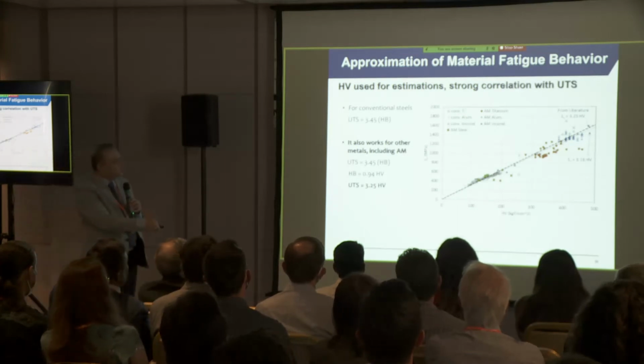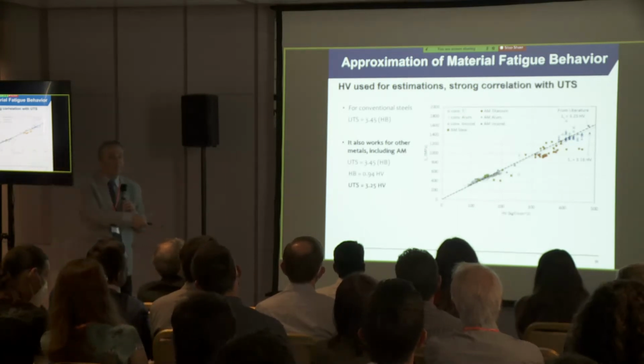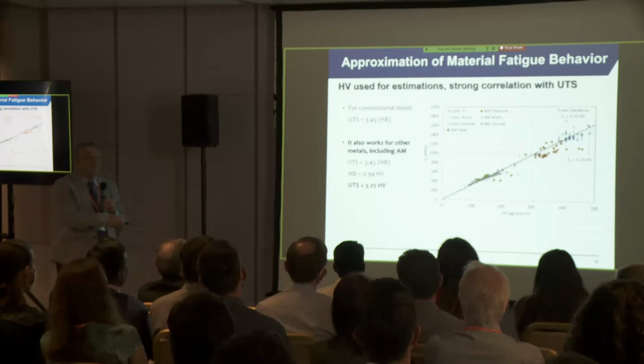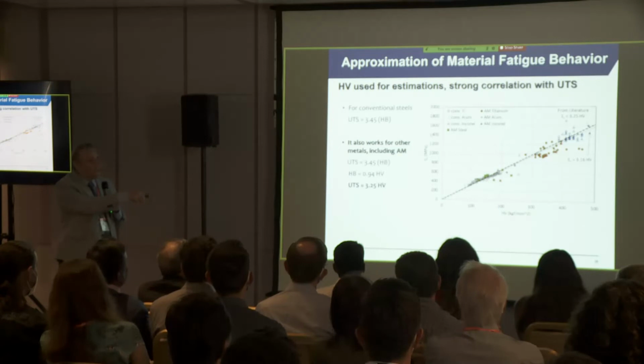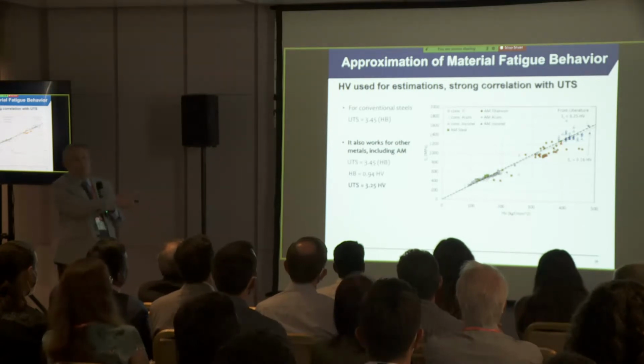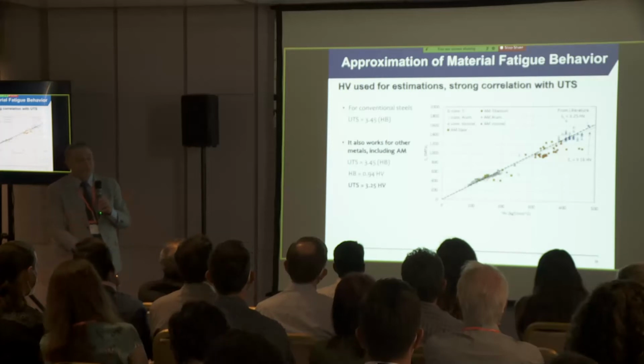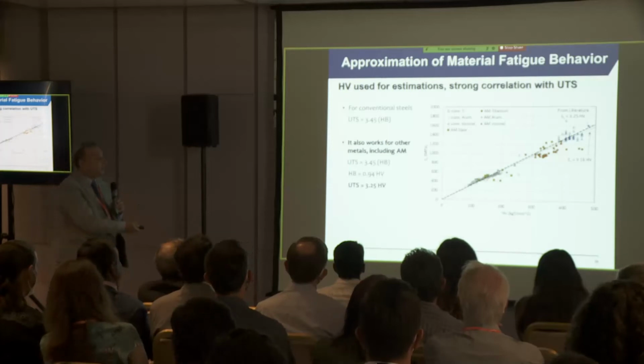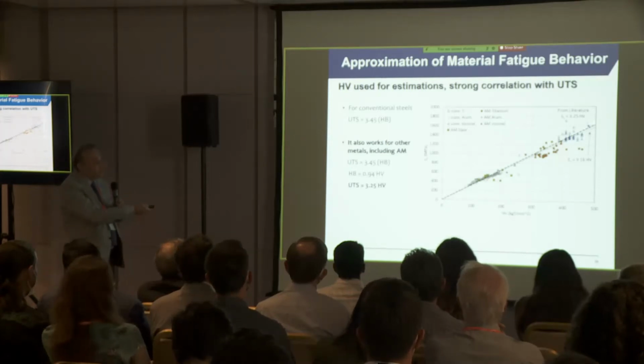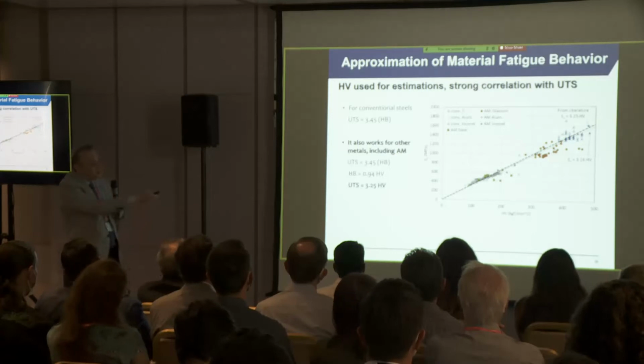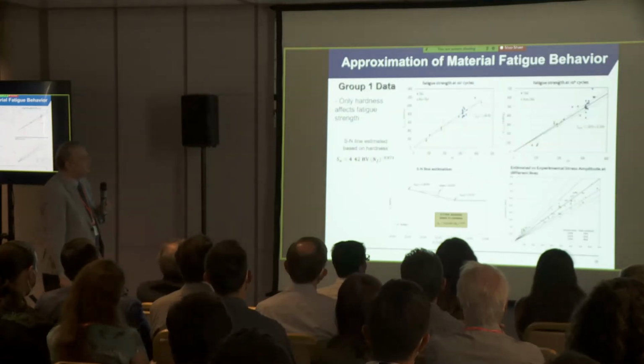What is shown here is ultimate tensile strength versus hardness. So rather than using ultimate tensile strength, we use hardness. But there is a good correlation between ultimate tensile strength and hardness. Traditionally, we have been using a relationship like this for metals, for steels in particular, but you can see with all of the additive manufactured data, the correlation also works well.